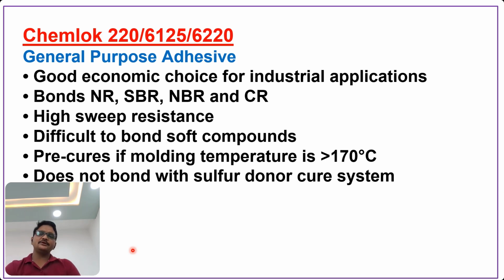This is a good economic choice for industrial applications on bonds: natural rubber, styrene butadiene rubber, nitrile butadiene rubber, and chloro rubbers like acrylic rubbers. High creep resistance and difficult to bond soft compound. Pre-cures if molding temperature is greater than 170. Means there is a molding temperature limitation in 6220 compound or adhesive or cover coat.